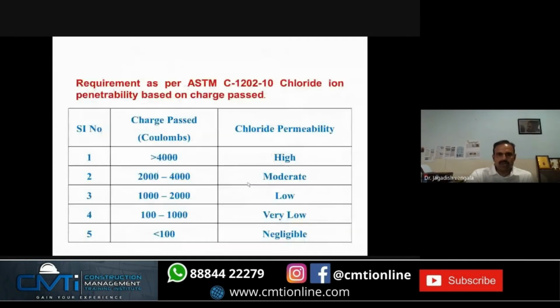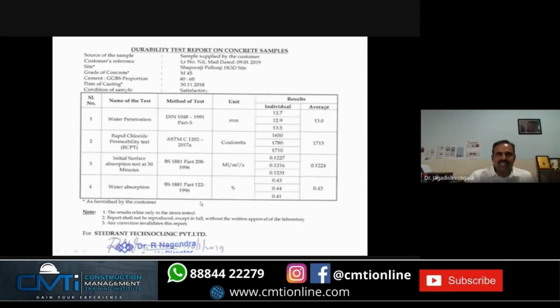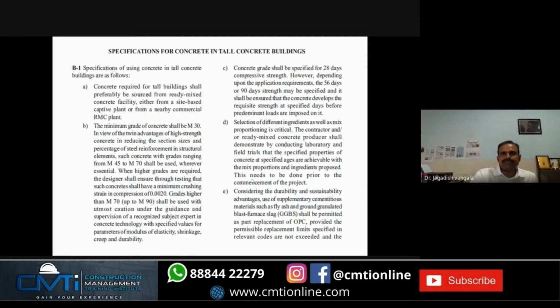Here I would like to show some of the values. See here, as per ASTM, more than 4000 is high chloride permeability, and low chloride is 1000 to 2000. One of the site tests conducted by Stedman, one of the sites at Amravati, tower, they calculated this RCPT test wherein it has got low. Some of the trials, these are only trials tested by Stedman.